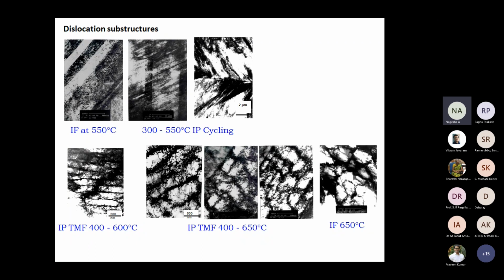So these are the typical dislocation structures that were observed under different testing conditions. We have carried out tests at various temperature ranges. This first big figure gives an isothermal test at 550 degrees centigrade, showing the typical dislocation arrangements seen. Planar slip bands were mostly seen. As the temperature increased, the dislocation structure changed to a wall-like or cell-like arrangement. Normally these steels are very prone to dynamic strain aging, with the effects peaking almost in the range of 550 to 600 degrees centigrade.